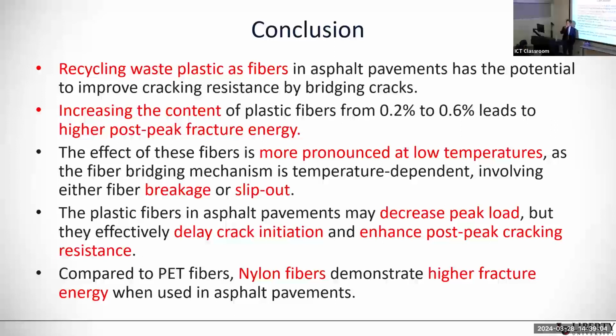But in asphalt, we have fracture failure, the cracking usually happening at low temperature. So that's why we see the cracking resistance at the low temperature or at room temperature with a higher loading rate. So it behaves differently at different temperatures.